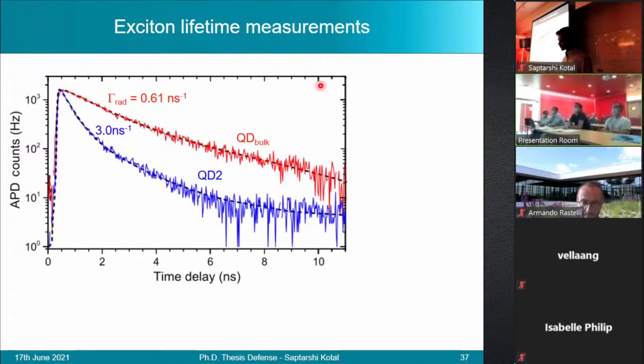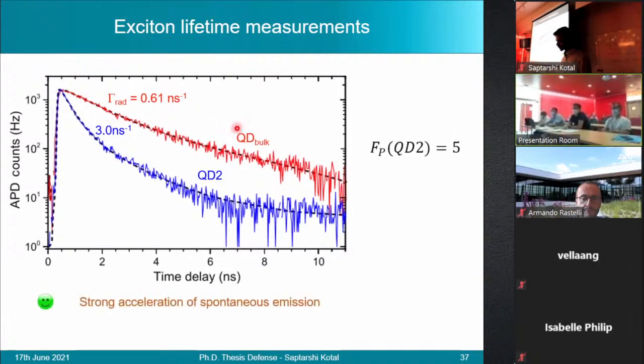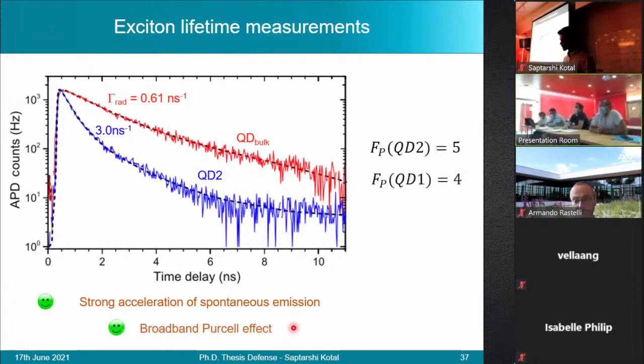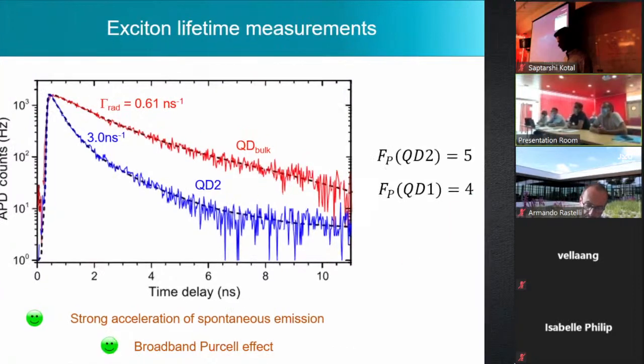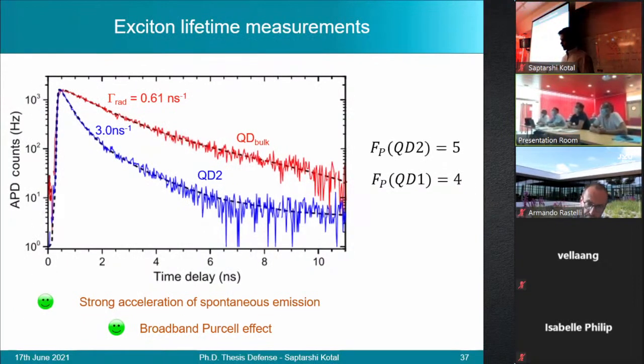Next, I show the graph of the charged exciton QD2. And as we see, it represents a lifetime which is 5 times shorter than that of the bulk. Additionally, a similar measurement on QD1 also showed an elevated spontaneous emission acceleration of around 4. And this is a good sign of the strong acceleration that our nanocavities produce.